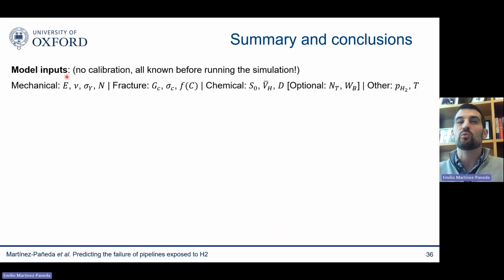So on the mechanical side of things, we need Young's modulus, Poisson ratio, yield stress, strain hardening exponent. So basically a uniaxial stress-strain curve. From the fracture perspective, we need the toughness, we need the strength, and we need the degradation of how the fracture toughness degrades with hydrogen concentration, the hydrogen degradation function. So basically, fracture tests at different hydrogen concentrations.